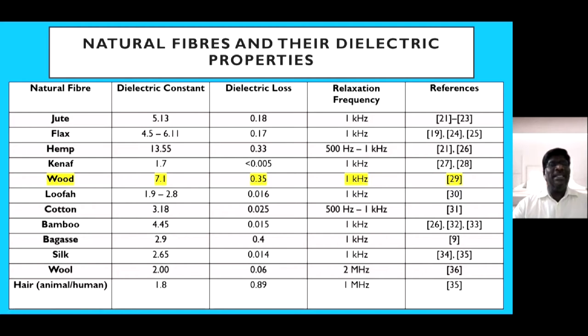Each and every natural fiber behaves differently, depending upon its nature of growing. This wood, especially Sarawak acacia wood, has a dielectric constant of 7.1, a loss factor of 0.35, and then the relaxation frequency. So from this literature, what we know is that wood contains a high dielectric constant. So this is a potential candidate for preparing electrical and electronic devices made of polymer matrix composites as well.